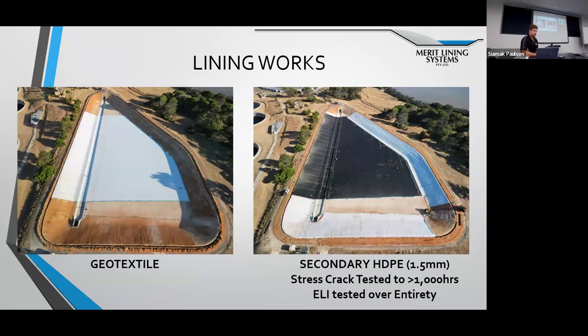So now to the lining works. You'll see there was 4 layers in this pond. We had on the left the first layer geotextile, on the right a secondary HDPE 1.5mm. This material was stress crack tested to 1,000 hours and ELI tested over its entirety.